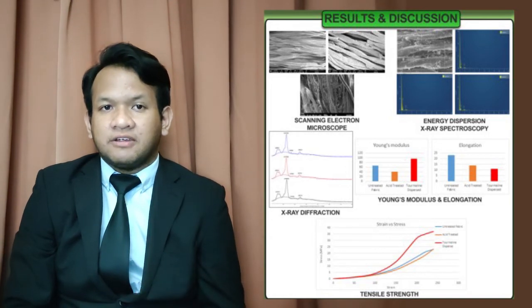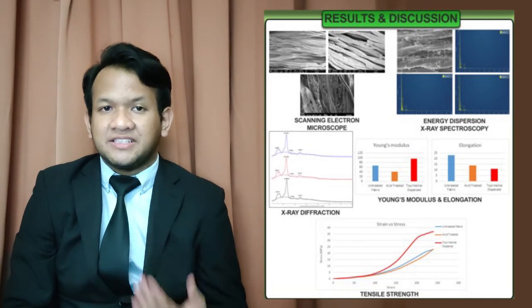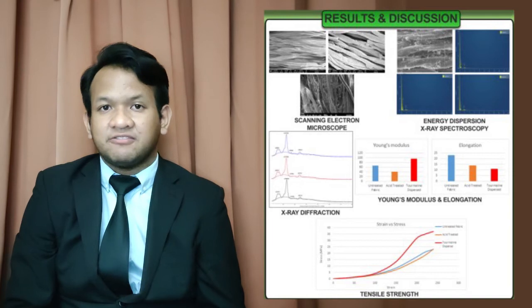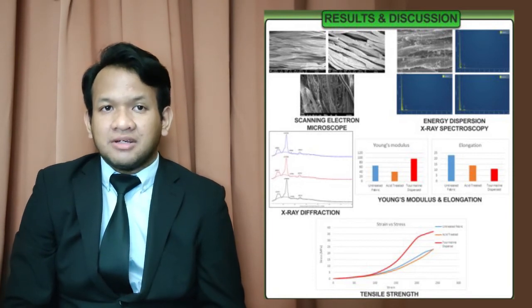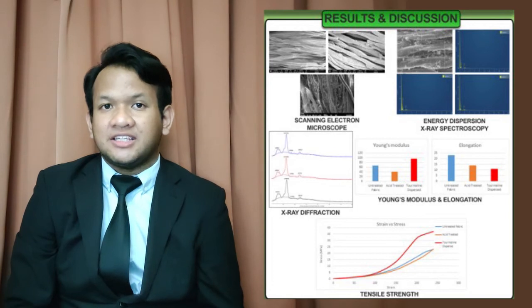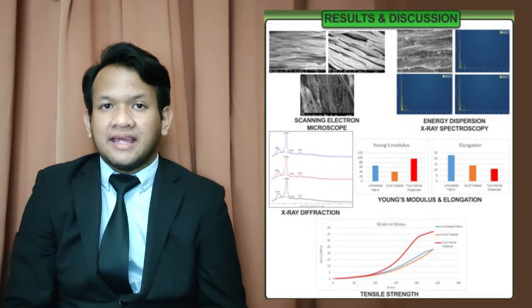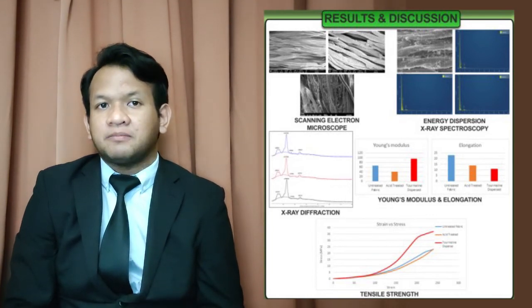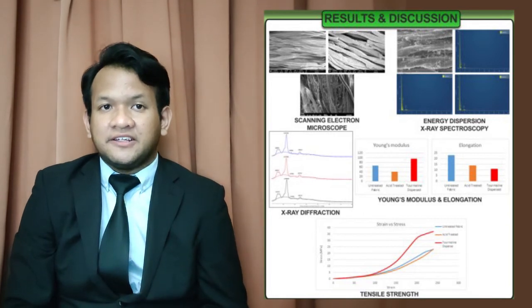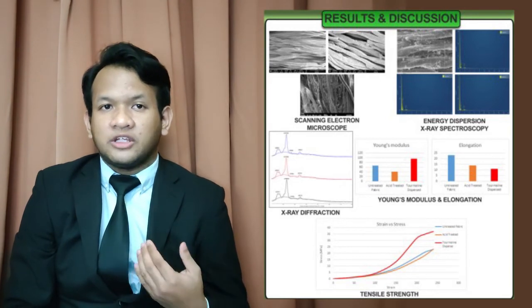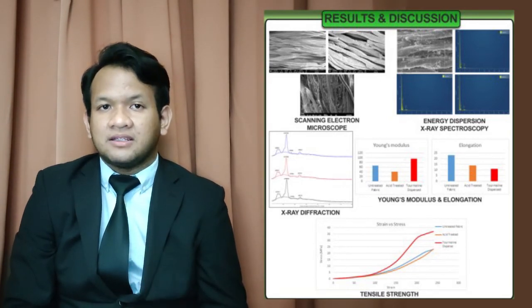On the tourmaline-treated fabric image, small bits can be seen on the treated surface, indicating the presence of tourmaline particles on the fabric surface. The tourmaline might have reacted early with glutaraldehyde during dispersion solution preparation, causing the tourmaline to clump together and attach on the fabric surface instead of being properly dispersed into the fabric thread. The early reaction during the dispersion preparation resulted in a small reaction rate to infuse the mineral onto the fabric, thus making it unable to evenly spread the tourmaline particles on the fabric surface.